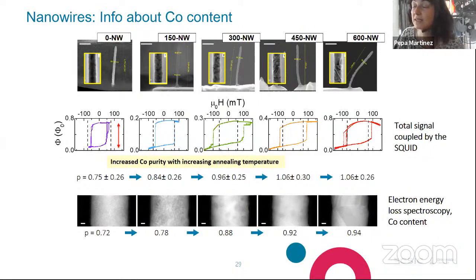Yeah, the spatial resolution will in the end be given by the size of the nanoloop, which is of the order of several hundred nanometers. So the best spatial resolution will be at best 100-200 nanometers.